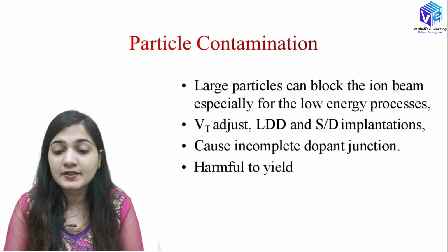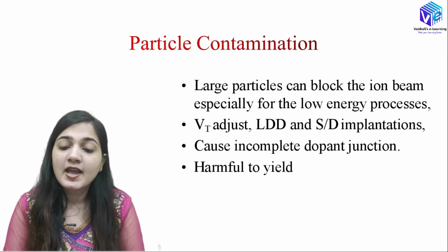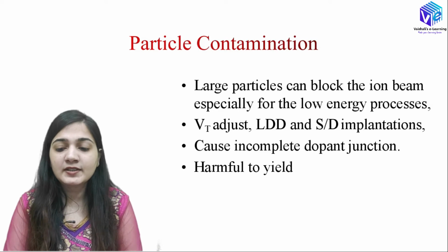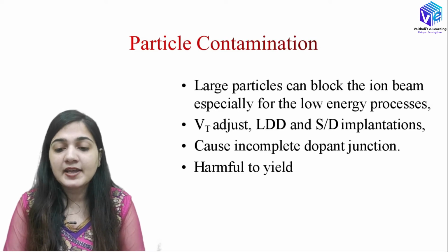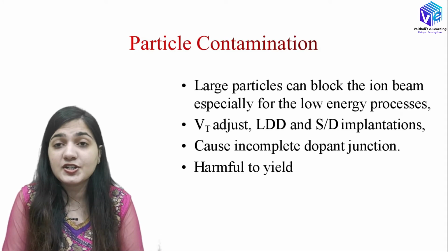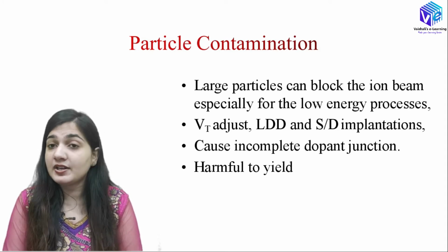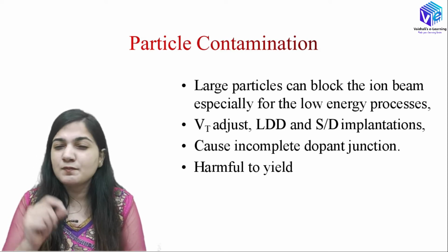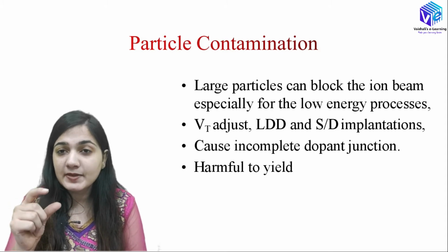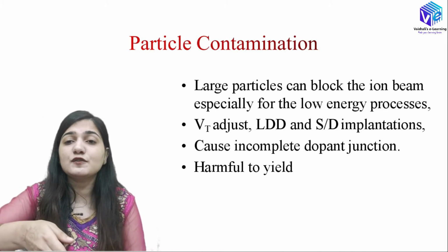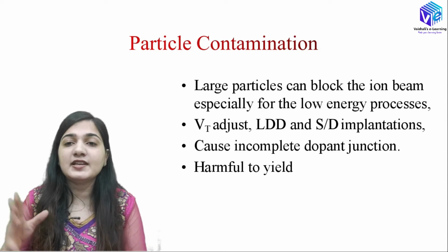Now it is present in all types of implantation like VT adjust, LDD and source-drain implantation. It is causing an incomplete dopant junction, and the large particles are blocking the ion beam, especially in the low energy processes. If I have a high energy process like the well implantation, the ion energy is so much that this contaminant particle is not affecting my process. The ion energy is so much that it easily removes these contaminants.